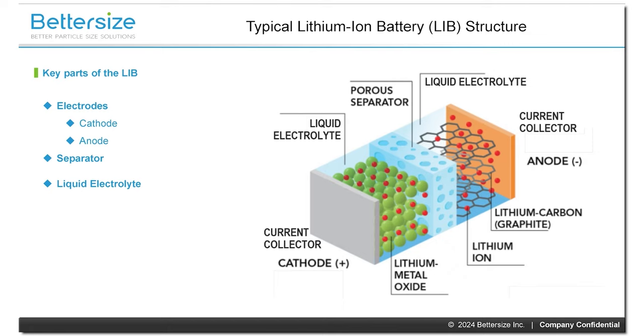If we look at this diagram, we can see the key components of the lithium-ion battery. On the right, we have the anode. It stores and releases lithium ions to the cathode in a process called intercalation, which is the reversible inclusion of the ions into compounds with layered structures. In this case, the anode is composed of graphite powder, and we also have a copper current collector on the right. On the left, we see the positive electrode, the cathode. This is typically a lithium-based metal oxide or phosphate, and on the end, we see an aluminum current collector. The cathode is the source of lithium ions and determines the capacity and voltage of the battery.